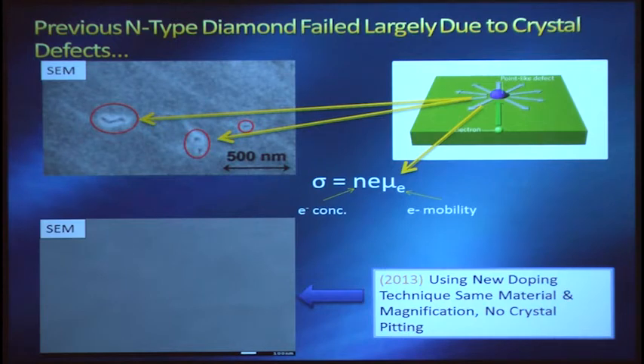So more recently, in our work at CNM, we were able to show, using a new doping technique, that with that same single crystal diamond, under the same magnification, there's no more pitting. So how were we able to accomplish that?